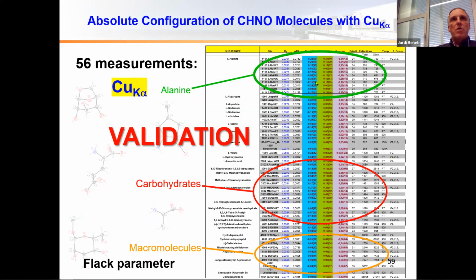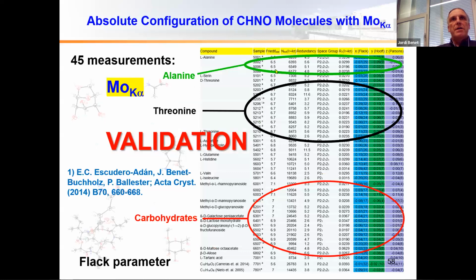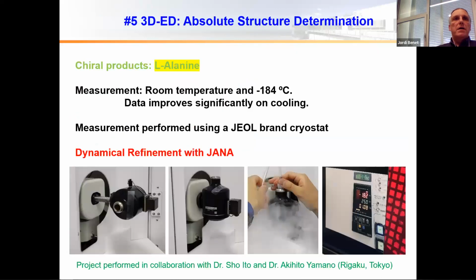You can see that our first molecule, always in this screening or test, was one of the smallest molecules available among the amino acids, which is alanine. And we were able to get the proper absolute configuration of this molecule although it doesn't have heavy atoms and it's a very small molecule. This is one of the most problematic ones. Also threonine. And so we went up to bigger molecules, up to big sugars. And now the question is, can we do absolute configuration determination using 3D-ED? And is it somehow validated?